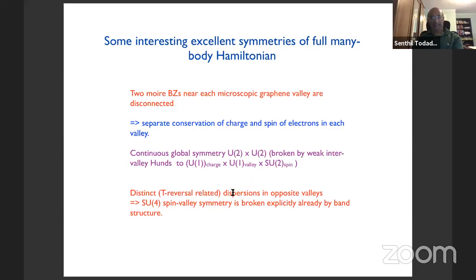Now, I should emphasize that the dispersions in the opposite valleys are distinct. They're related by time reversal, but they're really distinct dispersions. So at the microscopic level, there is no SU(4) spin valley symmetry. Again, those of you who work on graphene, ordinary graphene, may know about SU(4) spin valley symmetry that plays a role in some of the properties. But that is broken explicitly in this system already at the level of the band structure. Rather, the symmetry that you have is this as an approximate symmetry, and this as the even better symmetry.